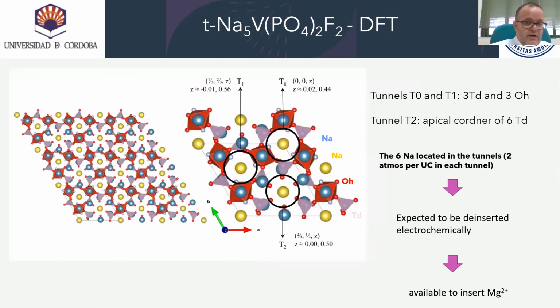Taking advantage of the reported results on sodium cells, as we saw before, we studied the adaptability of this material for magnesium cells. On the left is depicted the projection on the AB plane of the structure of trigonal NVPF. On the right, the three different tunnels in the structure running along the Z-axis, which are labeled T0, T1, and T2. The tunnels T0 and T1 are very similar, and they are formed by 3 PO4 and 3 VO6 units that share corners. On the other hand, the tunnel T2 is formed by the apical corners of 6 PO4 units.